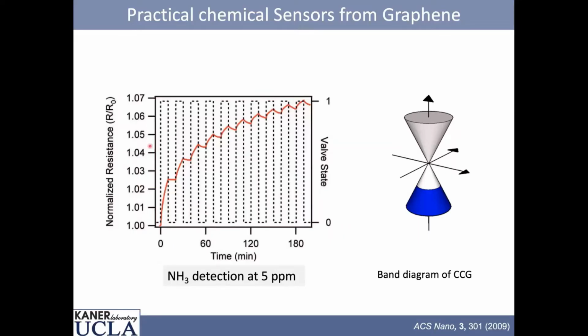And so what I'm showing you here is our material, our graphene from graphite oxide. We're looking at normalized resistance versus time. We're bringing up ammonia, which is a good electron donor, at 5 parts per million. And every time it sees some ammonia, you'll see the resistance goes up. So what are we doing? Here's our material that we're starting with. It's already slightly oxidized. And what we're simply doing is adding in electrons. So what we believe is we're filling in states in the valence band and the resistance goes up. We're making it less conductive.